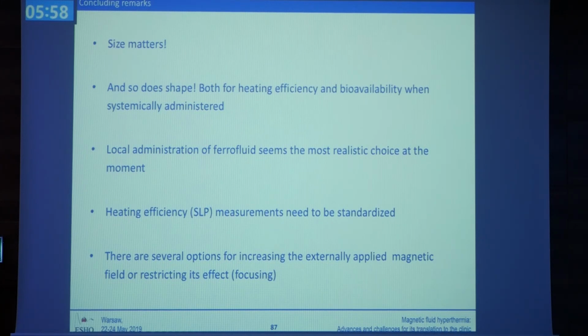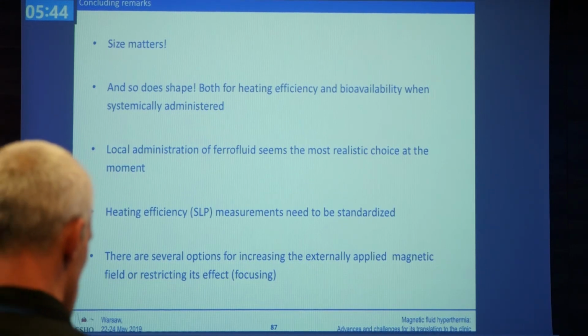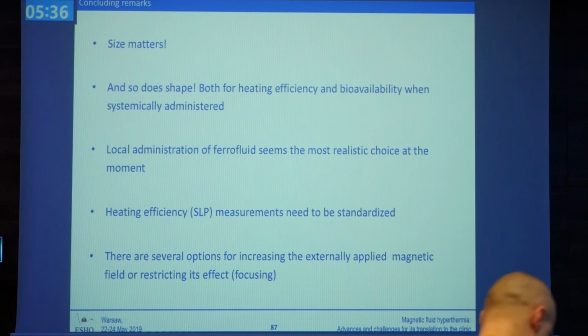Then it appears that for the moment we have this challenge, but local administration seems to be the most realistic choice for magnetic fluid hyperthermia. As I have shown you, we measure the SLP, the heating efficiency of the nanoparticles, with a lot of uncertainty, which needs to be standardized. So not only the synthesis, but the International Organization for Standardization should also do something about measurement of the heating efficiency of the nanoparticles. And there are several options for increasing the external applied magnetic field or reducing its effect. For example, focused hyperthermia is something we try in our lab in vitro and with agarose phantoms.